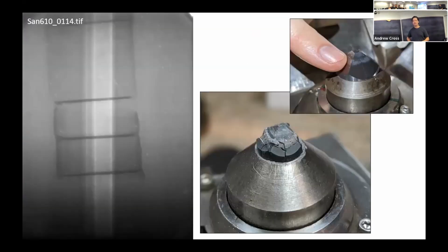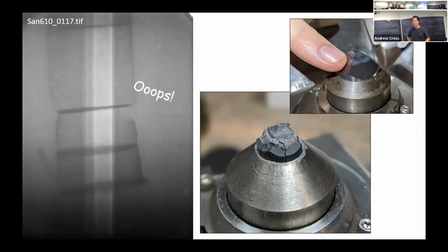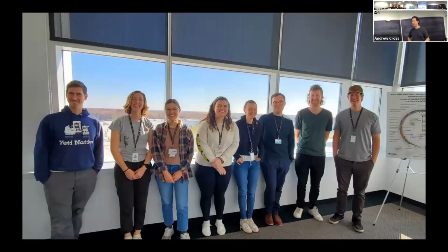And then finally, some science gone wrong. In keeping with the Halloween theme, Elvira tipped me off. This is an experiment from earlier in the week. We were trying to heat and anneal a coesite single crystal, but we inadvertently melted our nickel jacket, and so you've got these blebs of nickel coming away. And then we've got a cracked tungsten carbide anvil. I don't even know what happened here, but we somehow shattered a sintered diamond anvil. This was quite spectacular.